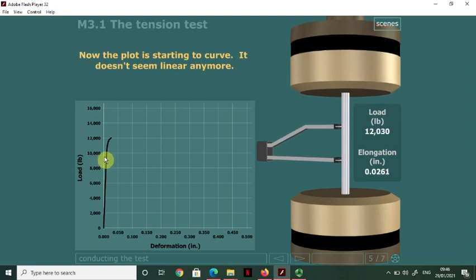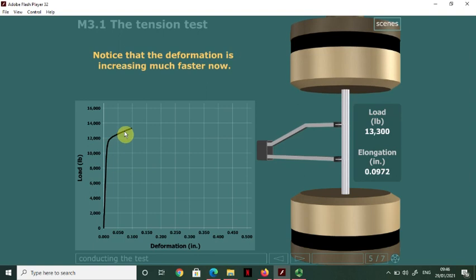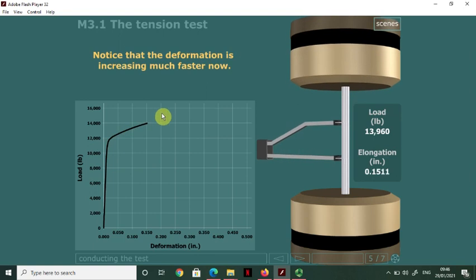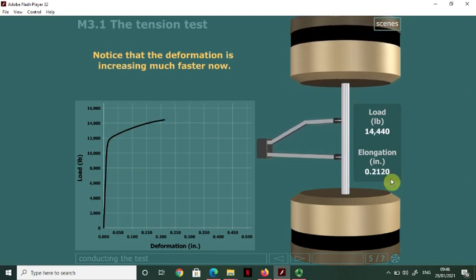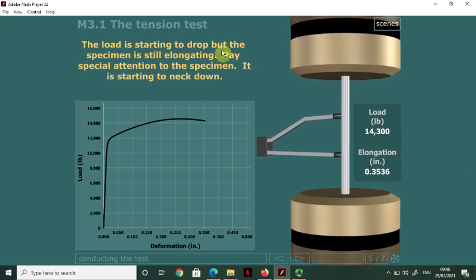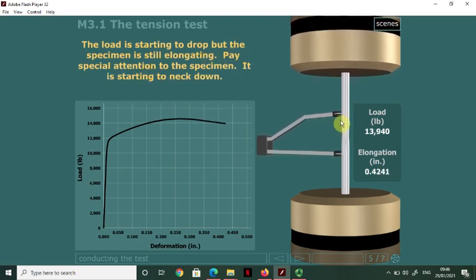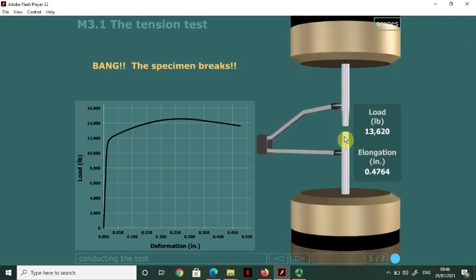And you can see the plot initially is very linear, but now it has started to curve. And the deformation is increasing much faster now. You can see the elongation is increasing much faster. The load is then starting to drop, but the specimen is still elongating, and you can now see some reduction in the area as well. That resulted in the neck and then final fracture. So these are the typical features that you see before the final specimen failure or the bang.